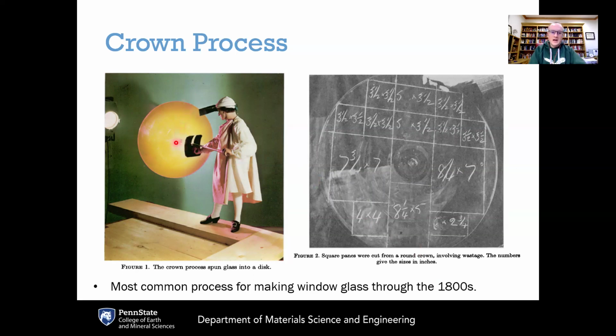This involved taking a gob of glass, sticking it at the end of a rod here and spinning it, and then it would spin out into a disc. That disc of glass would be cut up into pieces that could be put into the stained glass window. And of course, the glass would be thicker in the middle compared to the outer parts. And so there would be thickness non-uniformity in the glass because of the way that it was being made. And then when the stained glass artisan would put it in place, it's only natural to put the thicker part in the bottom because that gives at least the appearance of greater stability rather than having the thicker part at the top.